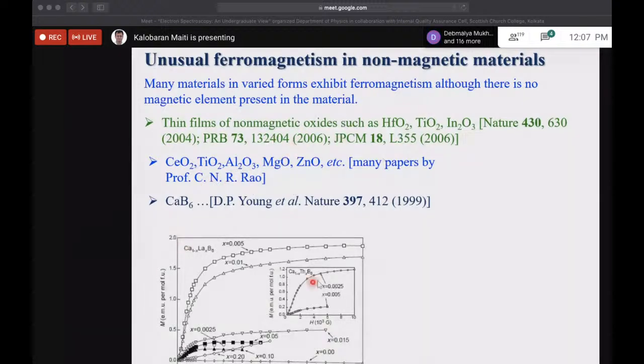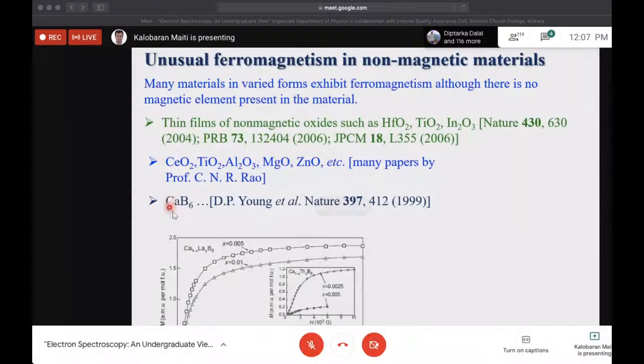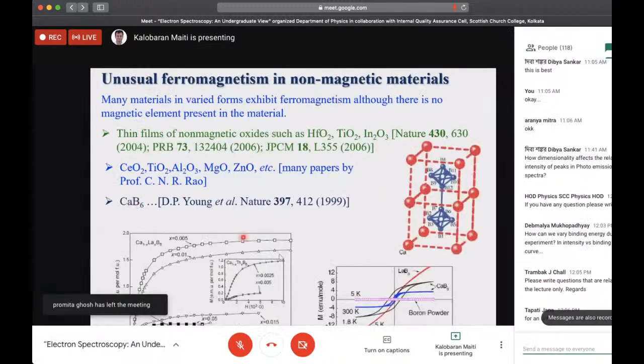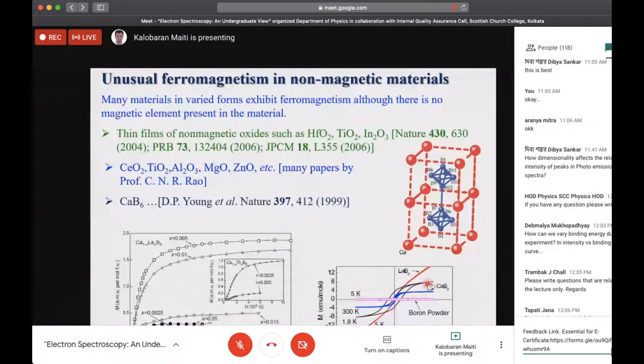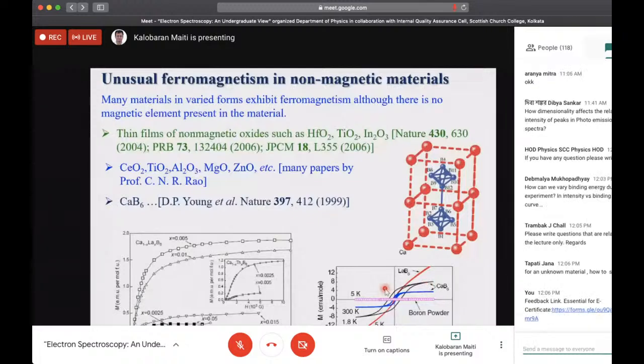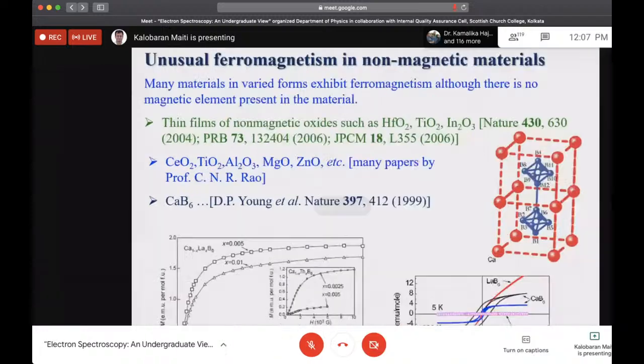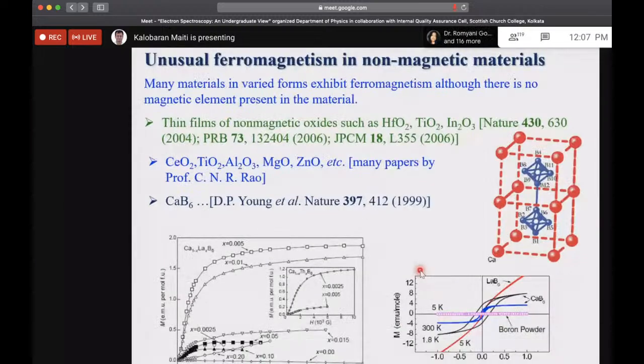I'll show you one example, calcium hexaboride. Calcium is not a magnetic element. Boron is not a magnetic element. But if you do magnetization, you see that it shows a hysteresis. So it's very funny. And not only that, the Curie temperature is very, very high, something like 600, 700 degrees centigrade. I mean, 700 Kelvin. So this is a very unusual kind of thing.